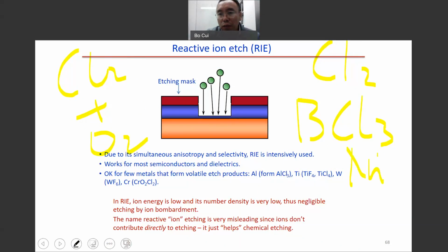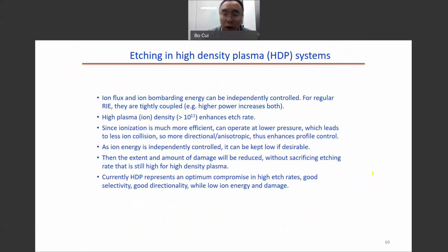Nickel is very difficult to etch. The same is true for gold. The gold is also difficult to etch in the plasma. We can etch it in the plasma, but it's mainly ion bombardment. There's not much chemical reaction in it. Because the regular RIE process is a low density plasma, the etching is not very efficient. So the solution is to have high density plasma.